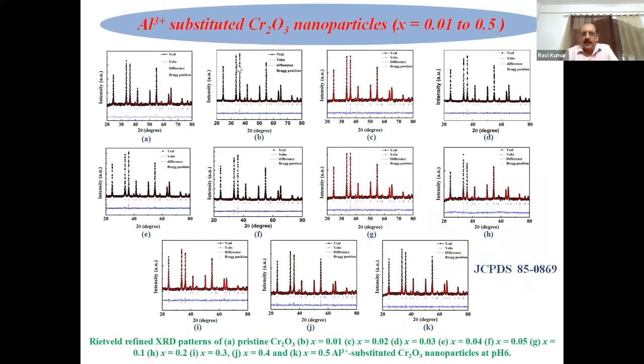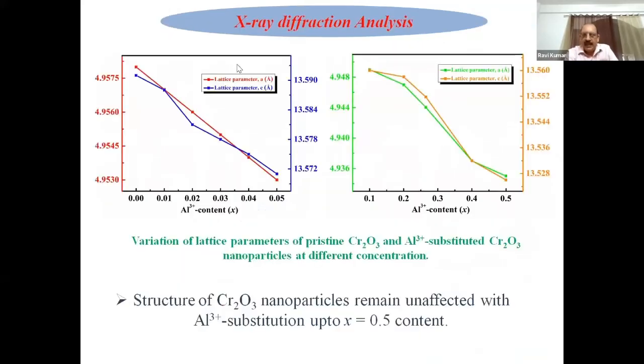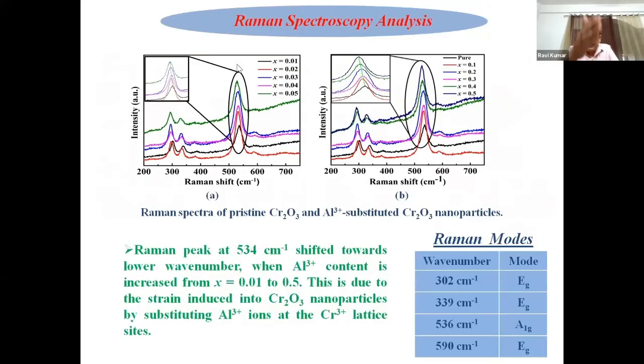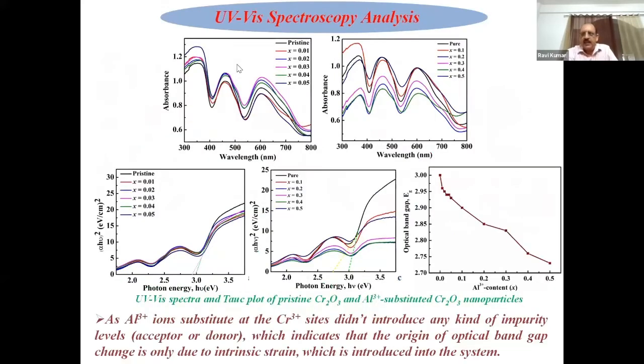So you have a change in the band gap. Now a similar experiment we can do with the aluminium also. Aluminium is also showing a single phase, and then lattice parameters are decreasing. Then there is again a strain in the Raman, and again the band gap is decreasing with the aluminium also. This is a powder. So far all these measurements are on powder.